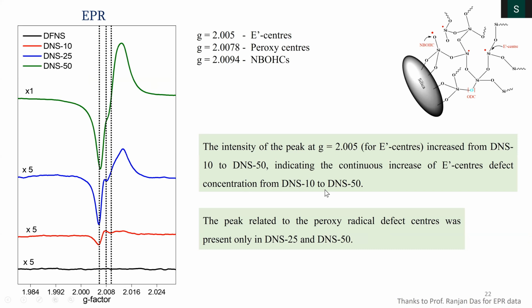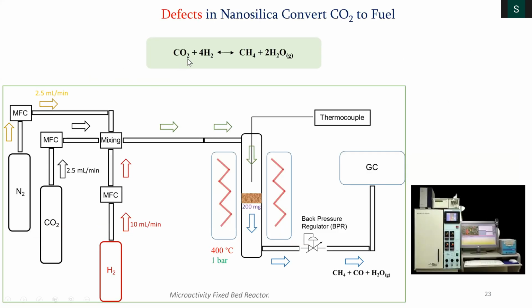With these characterizations, we went ahead to see whether they can be catalytically active. We tested these reactions, CO2 plus hydrogen to get you methane plus water, and there is something missing, which is plus CO, carbon monoxide. So you take CO2, you take hydrogen, mix them, and then this is your catalytic reactor. You have the catalyst here, which is heated at 400 degrees Celsius, 1 bar. You pass the gas, and then you monitor by online GC the product formation: methane, CO, and water. Water you don't monitor, but you get it in the other reactor. So methane and CO ideally.